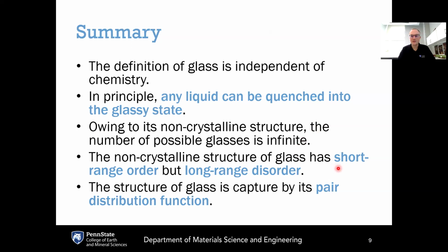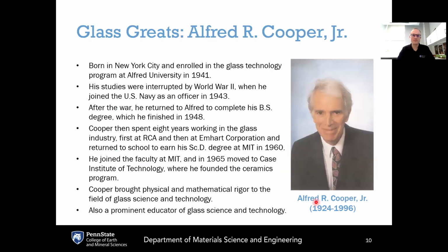But that doesn't mean that the structure is completely disordered. What we know is that the non-crystalline structure of glass actually exhibits some short-range order, meaning that the first nearest neighbor is fairly well defined. But if you go to longer range distances, we have disorder at those longer distances. And we can quantify the structure of glass. It's captured by its pair distribution function, or equivalently, the radial distribution function.